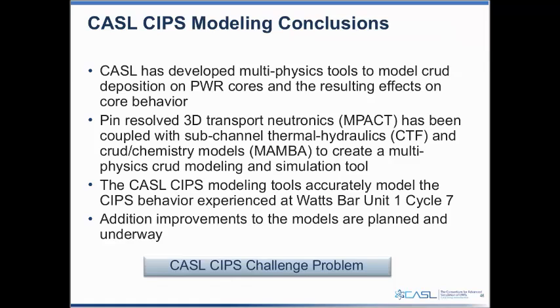So just to summarize our initial CIPS modeling, we're quite pleased with these results so far. This is the first time we've been able to do a full quarter core simulation of crud with the CASL tools. As Brian Kendrick had mentioned, we'd had several other multi-rod simulations or even up to a full fuel assembly. But this is the first time we've done a whole quarter core simulation for an actual core that did experience CIPS. So we took the multiphysics tools that CASL had developed and applied those to WattsBar to model crud deposition on the core and the resulting effect on core power distribution.